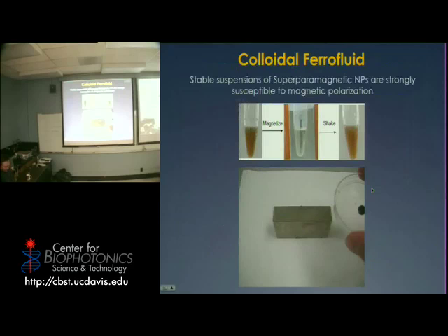I actually have some if you guys want to see, but in the biomedical sense, we call these ferrofluids. So you have a suspension of these particles, it's colloidal like the gold, but in this case it's magnetic. And they give you a clear solution and everything. If you put them close to a magnet, they go to the magnet. But when you remove the magnet and shake them up, they go back. And in actuality, this is the behavior of the larger ones. The ones that are smaller don't do this in the sense that they don't really aggregate, but they have properties like this.